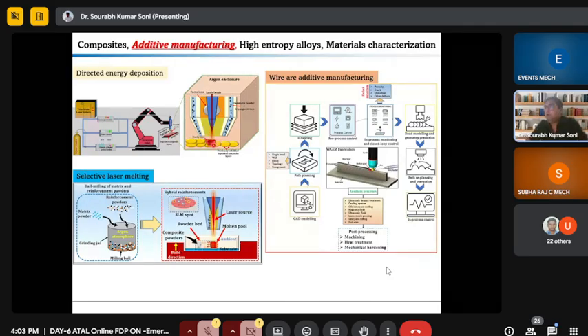used. In DED, what we are doing, we are depositing the powder layer by layer, followed by heating and melting to get the final composite specimen. But in SLM, what is going on? Powder bed is already there. We will use the laser source to melt the powder and layer by layer deposition to form the composite specimen.